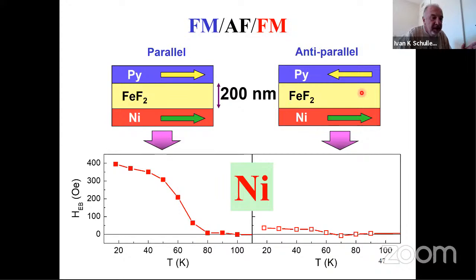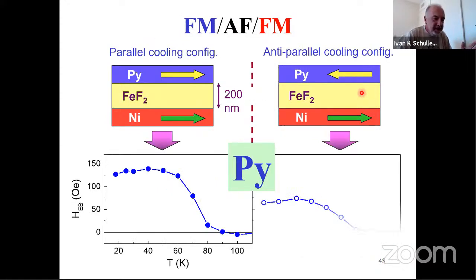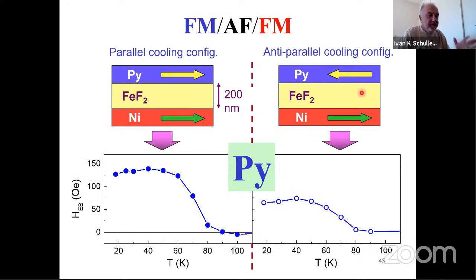If I do the same thing with the permalloy, guess what? Exactly the same thing happens. Whether the two layers are parallel or anti-parallel to each other, the exchange bias at this interface is different depending on what the bottom layer does. It shouldn't be, if it were a purely interfacial effect. As I'm telling you, this has been confirmed by many other measurements, which I don't want to bore you with.